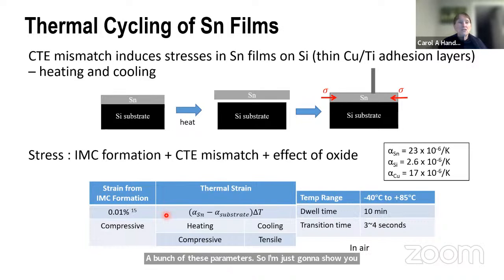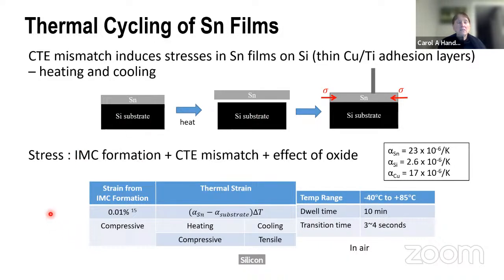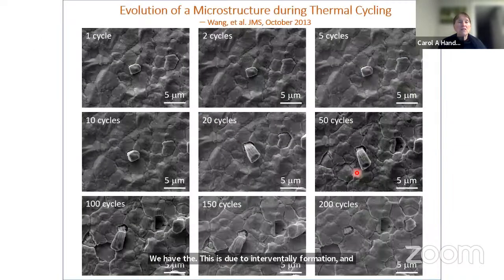This is CTE induced stresses in tin films on silicon. So it's heating and cooling. So we have the silicon substrates. And so in this case, we have the stresses due to intermetallic formation and CTE mismatch, and we have the effect of the oxides. We have all of these.